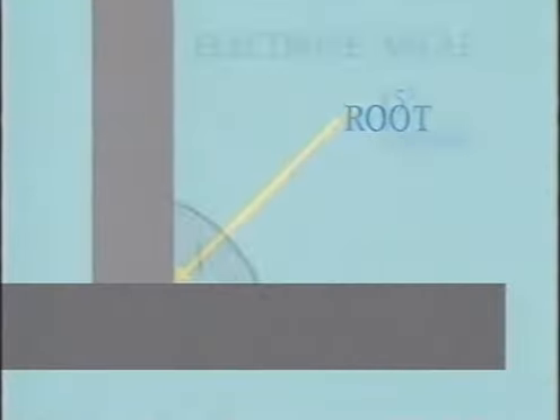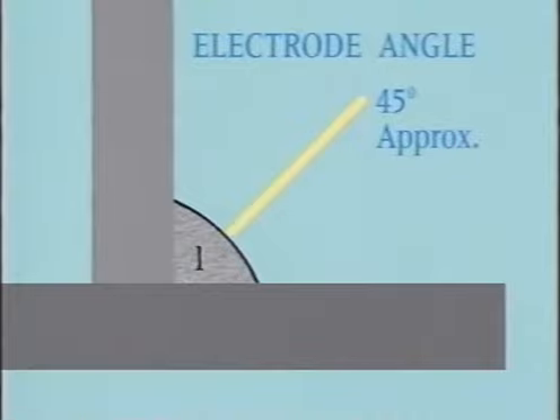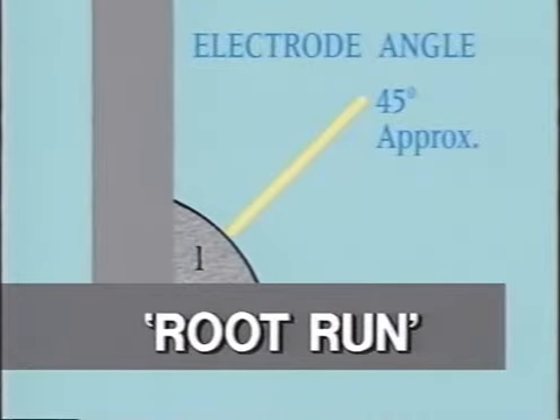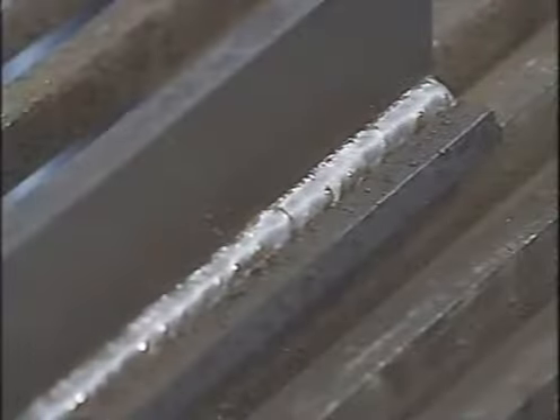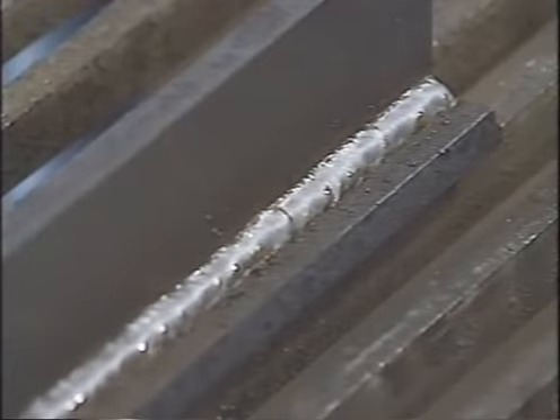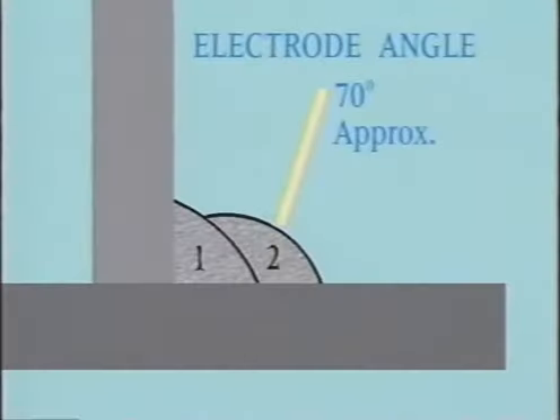When using thicker pieces of plate, welding can be accomplished by using multiple passes, or weld runs. The number of weld runs is determined by the thickness of the plate and the wire diameter. The technique is the same when depositing the first weld bead, which we call the root run. Check the weld, then deposit the second run. The gun angle should be approximately 70 degrees from the horizontal.